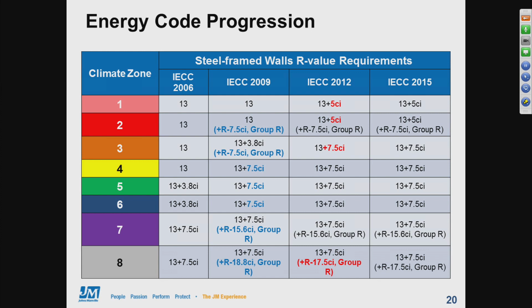If we just consider steel-framed walls, and if we start back at the 2006 version of the Energy Code, continuous insulation was really only required in what we would call cold climates, zones 5 and above. This would be cities like Denver, Chicago, Boston, Minneapolis. In 2009, the code increased the CI R-value requirements in the cold climates and then extended where CI was needed all the way into climate zone 2, which is what we would consider a warm climate. Climate zone 2 would be cities like Houston or Phoenix.